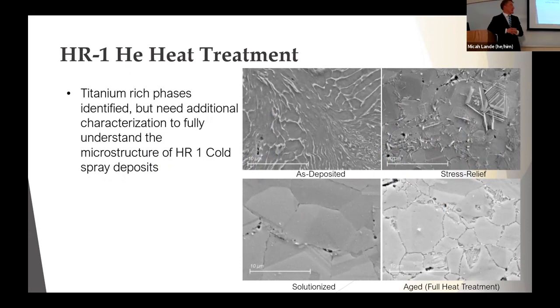If you remember me saying at the beginning about HR1, it has another crystal structure that we don't want to see, which is the eta phase. That is a nickel titanium rich phase, and it essentially acts like a stress concentrator, and it's especially susceptible to helium environment embrittlement. So we don't want to see that. Seeing that much of it on that scale is not a good thing. However, going into our solutionized step, we see a lot of that is pretty significantly reduced, almost gone altogether.